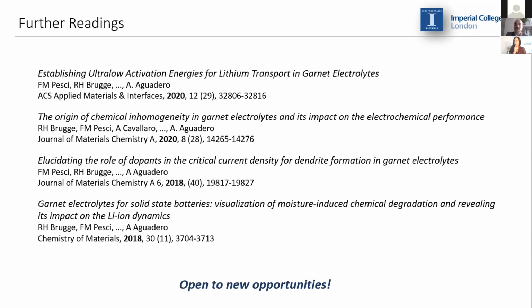Can I add that one of the most important things is to avoid moisture? So we do everything in a glove box, and we have a furnace coupled to the glove box. I think there is a question also about thermal etching. We do everything in the glove box, and that is very important because moisture reactivity degrades heavily the conductivity of garnets.